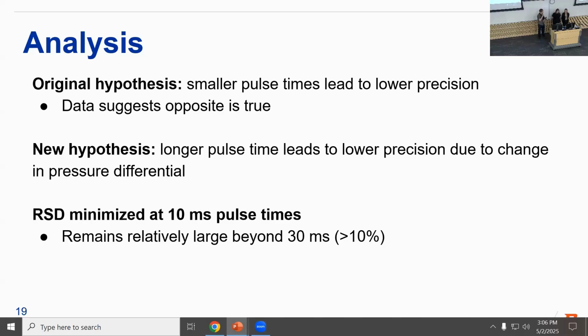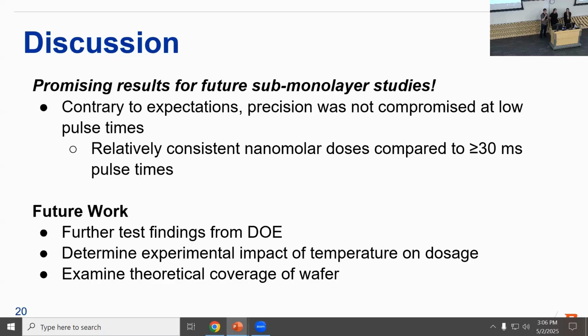But as that ALD valve is left open for longer periods of time, this gives more time for the gas to equilibrate, and the pressure differential changes during the dosing. We've attributed that to a greater variation in the gas dosage at longer pulse times. As Sarah was showing, we have the RSD minimized at 10 milliseconds, and that was the greatest precision out of all of our tests.